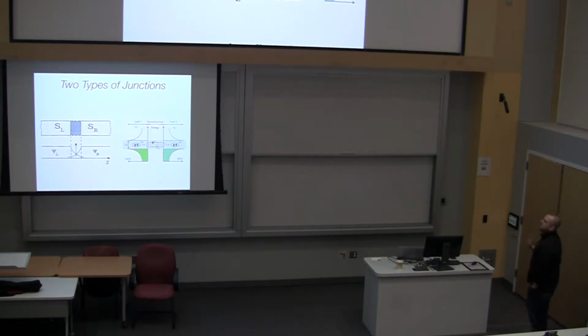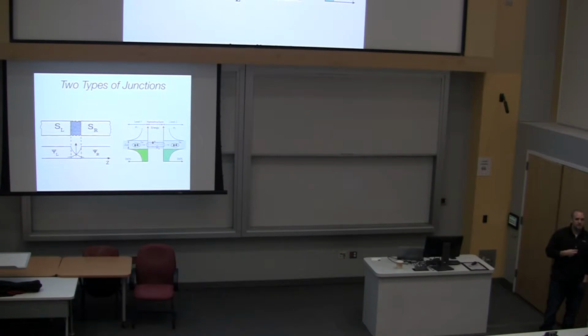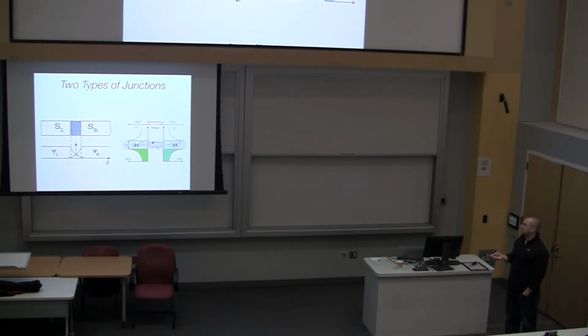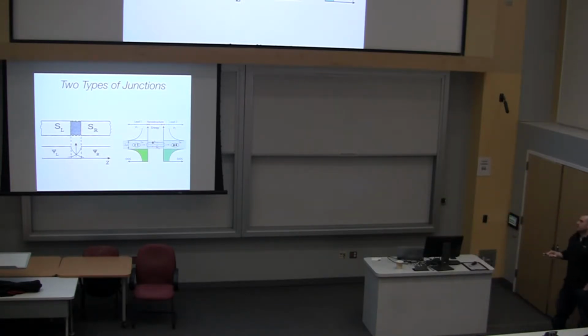And there the fundamental processes which govern the transfer of Cooper pairs are quite different. This is a cross-section of what we call an S-N-S junction, where you have two superconductors coupled by this conducting metallic layer. Inside this metallic layer, there are no Cooper pair-like excitations. There are only electron and hole-like excitations. So if a Cooper pair wants to be transferred from the left lead to the right lead, it needs to go through this normal region, and it can only go through as an electron or a hole. A Cooper pair basically eats up one of these holes that exists in the Fermi sea in the normal metal and spits out an electron. Before that electron can enter the second superconductor, it needs to pick up another electron to form the Cooper pair. And when it does, it creates a hole that is then retro-reflected back to the other junction. This process happens in a very Fabry-Perot-like interference pattern.